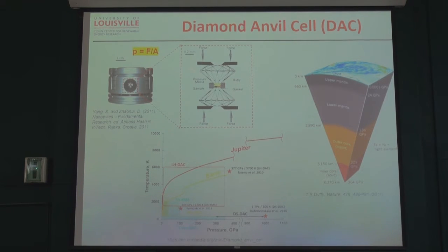Not only that, you can even do it at high temperature also. There's something called laser-heated diamond anvil cell. Laser heating, so you can use a laser to heat the material, right? Then you can get high temperature and also high pressure. This is like 300 gigapascal. We are working in the range of maybe hundreds of gigapascal. And which temperature? We are doing it at room temperature right now.